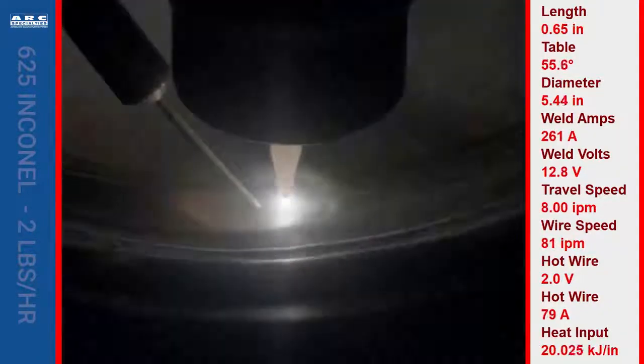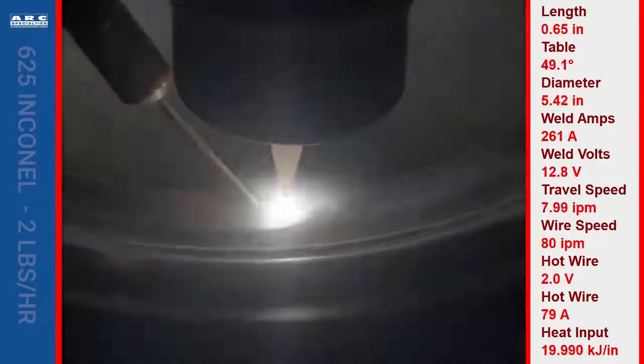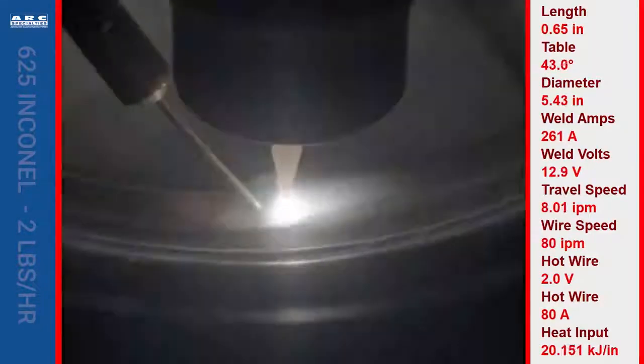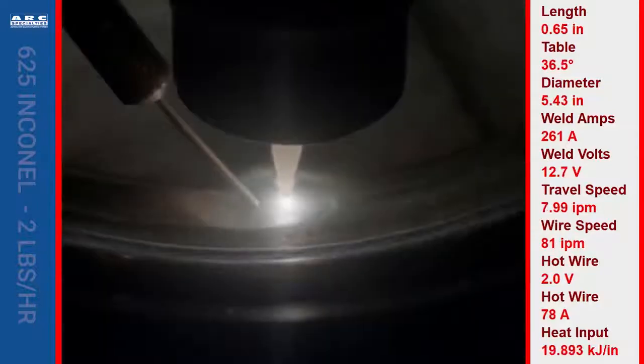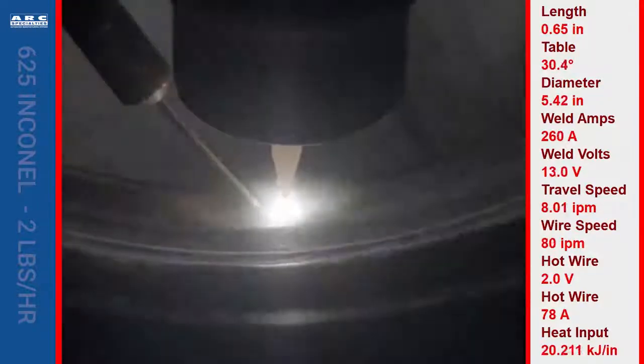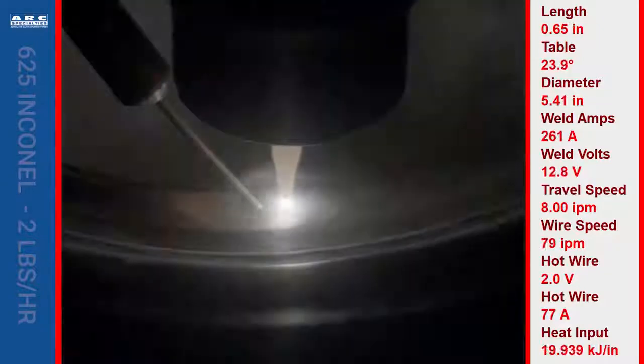What we're also able to do is create a weld with very low dilution. This is probably around 10% dilution in a single layer. So with 2 layers, we're well below the 5% dilution required by many corrosion-resistant alloy applications.